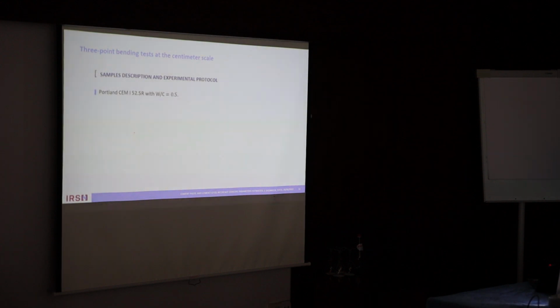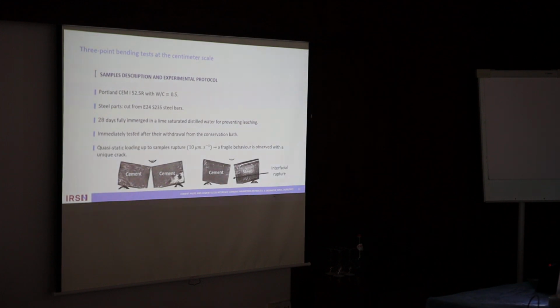So the cement I used was the same one, 52.5 R with a water cement ratio of 0.5. Steel bars were cut from steel bars having the desired cross-section. It was E24 S235 steel. Samples were conserved in lime saturated distilled water for 28 days. And they were immediately tested after having been withdrawn from the conservation bath under 3-point bending test with a quasi-static loading up to the sample failure.